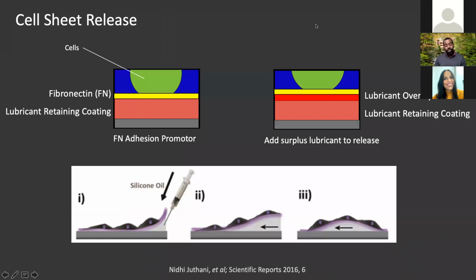So, that's just if you want things to not stick from the very beginning. But now that we're starting to approach this and have this as an approach in our design toolbox, we could start thinking of doing combinations of stick and non-stick systems. Say in a case where you want to grow a sheet of cells in a culture, you need some sort of adhesion promoter, so maybe fibronectin that will signal the cells that it's okay, that they can settle on the surface. And underneath that fibronectin film, we may have a lubricant retaining coating. It's not so actively slippery when we apply the fibronectin, we apply the cells, but after the cells have formed their sheet and we want to harvest them, one approach would be to inject lubricant underneath the cell sheet and allow that to interact with the lubricant retaining coating, become slippery, and then release the whole sheet as a whole, which can then be harvested maybe through transfer, maybe on a piece of filter paper or something, and then you can do with it whatever you wish.